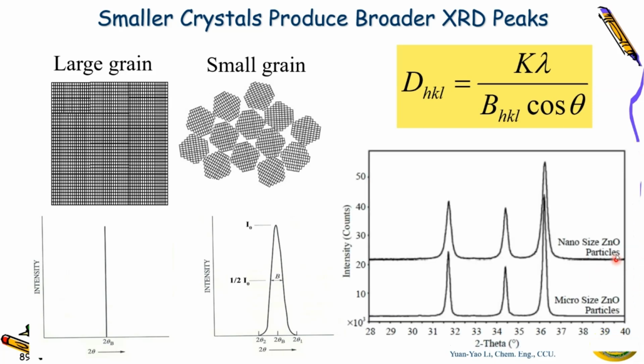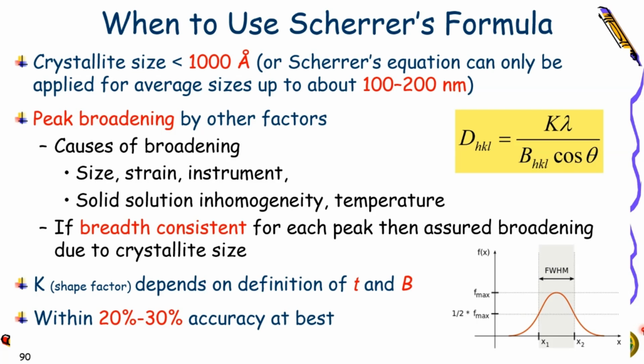So this is an example showing you zinc oxide. Nano size zinc oxide, you know the peak is broader. But micro size zinc oxide particle, the peak is sharper. I should say the peaks are all sharper, not only one, but also the others, they are all sharper. When to use the Scherrer formula: you cannot use the Scherrer formula for bulk particles that are very big, like millimeter or centimeter. The crystal size needs to be less than 100 nanometer, so normally it's about 100 to 200 nanometer.